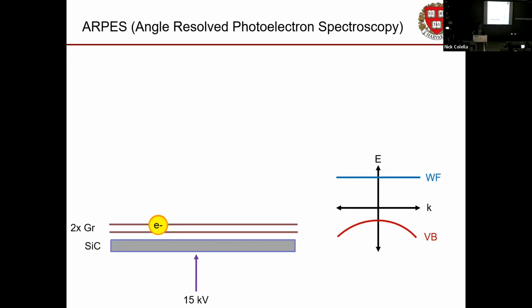What's ARPES? This is angle-resolved photoelectron spectroscopy. So starting with the same gimmick, we're going to shine light, we're going to get electrons out, but we're going to go a little further than that. This time I'm going to shine real high energy light, like 20, 40 eV light. So that's pretty ultraviolet light. We need to make a plasma out of helium. It's a whole fuss, but we can do it. And we shine the light on, and it's monochromatic. We're not using broad spectrum light anymore.